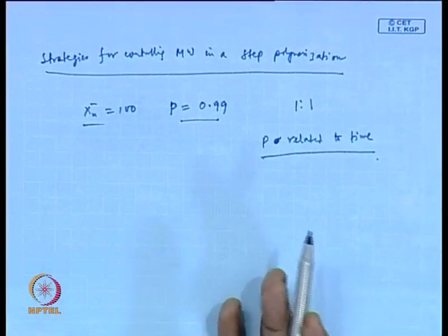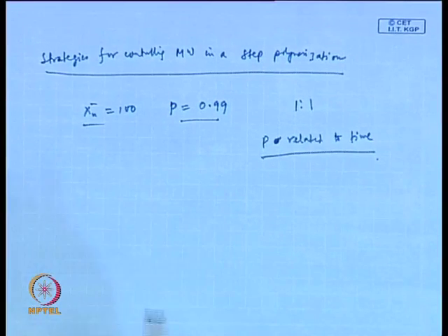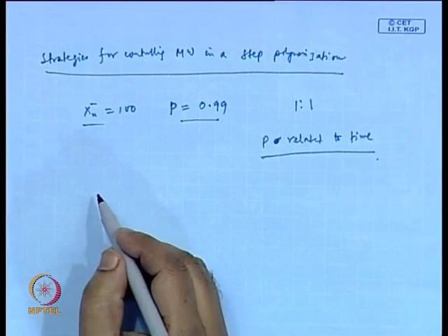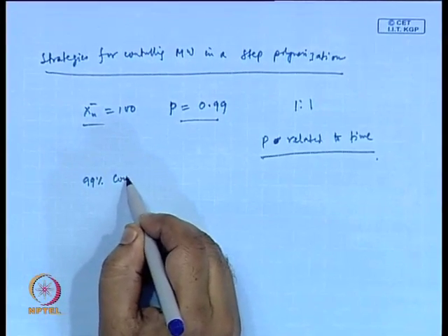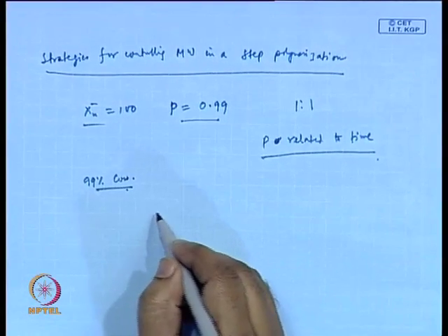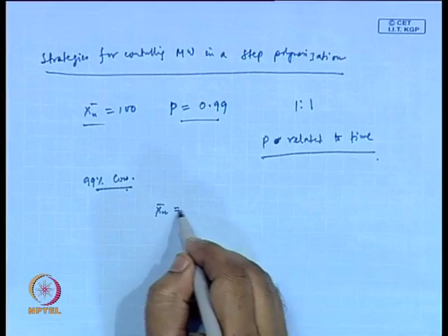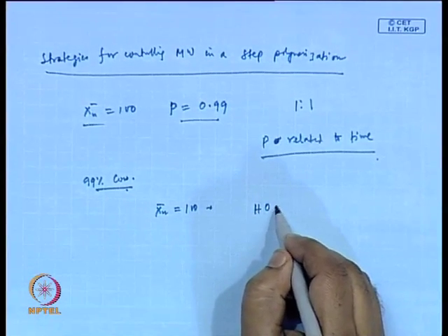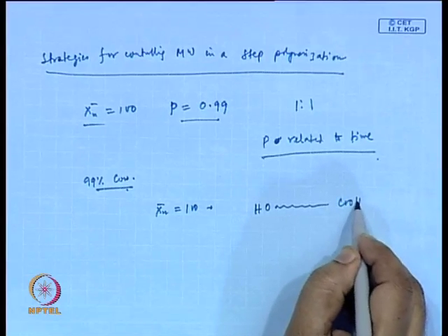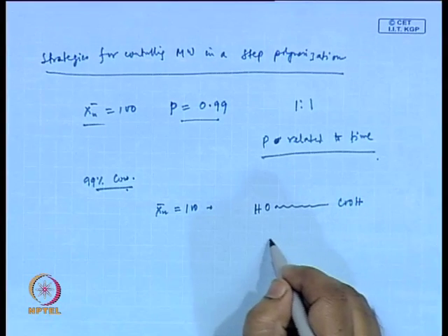But what is the problem in that? If you stop a reaction at a level of, say, 0.99 or 99% conversion, what do you get in hand? If you are talking about a polyesterification reaction, what do you get at the 99% conversion level? You get an average of 100, with functional groups on both sides, and you also may have some monomer present.